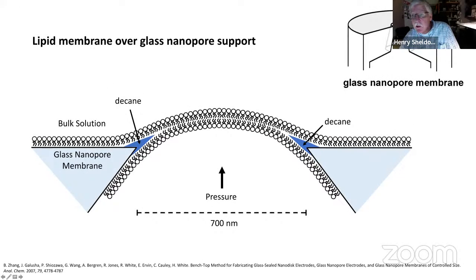So we use a structure. This is a glass structure up here at the right. There's a membrane with a little nanopore in it, and we paint a bilayer across the surface. I don't want to get into the details of this, but you have an aqueous solution up here, an aqueous solution up here, and the bilayer is deposited from a solution containing lipid dissolved in decane.